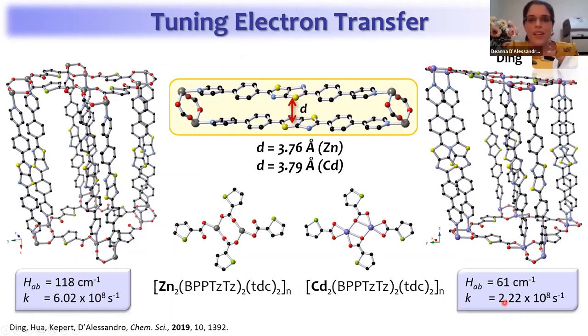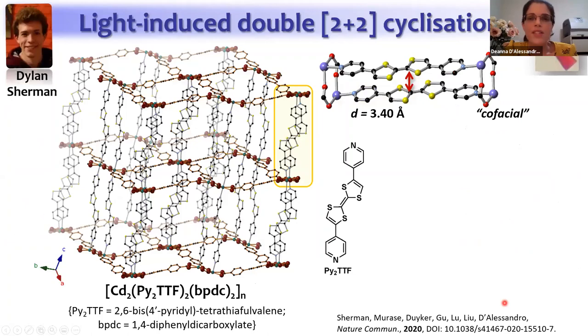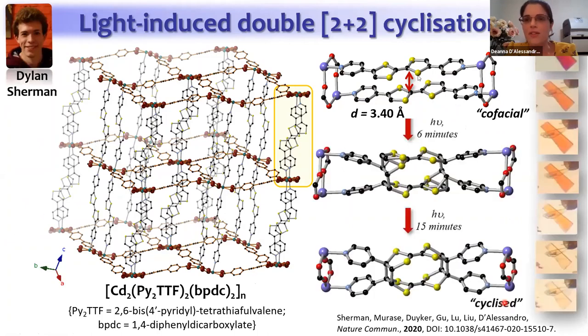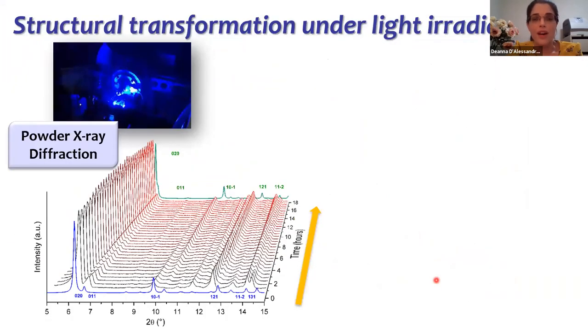So I want to talk about a really recent paper that we just published. This is a very similar framework with cofacial ligands, but now the cofacial ligands are tetrathiafulvalenes. What was interesting about this framework is that just leaving it on the bench over the course of a few minutes actually changed the framework from a red coloration to colorless. And using crystallography, we were able to ascertain that this was due to a double 2+2 photocyclization of these electroactive tetrathiafulvalene ligands. Now we could follow this using powder X-ray diffraction, and we could determine that we were indeed altering the cofacial structure to the photocyclized structure.